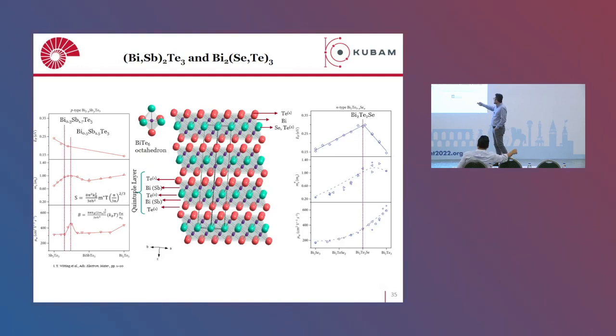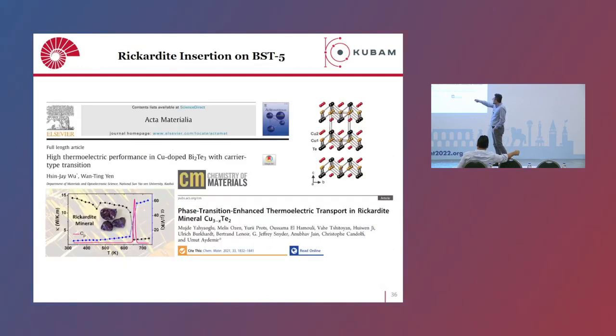So when we were dealing with this research, we found that there are a couple of research publications dealing with bismuth telluride doped with copper, getting better efficiencies. Now, we don't want to repeat that, but we have copper telluride, which can act like a copper source, and at the same time shows a strange phase transition and is metallic. We thought, rather than using pure copper, why don't we use copper telluride? Because copper is a mobile ion in copper telluride as well. It has high ionic mobility. It can diffuse easily into bismuth antimony telluride, perfectly fine.